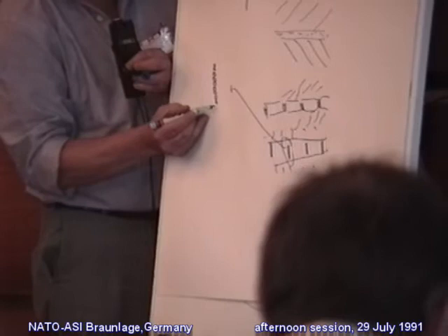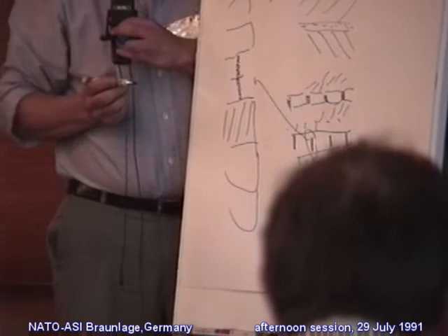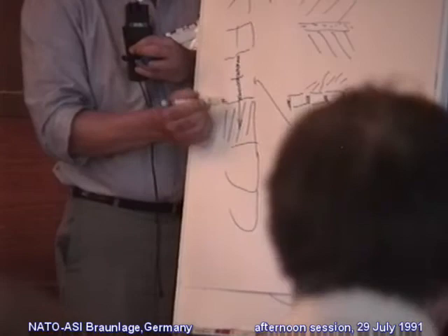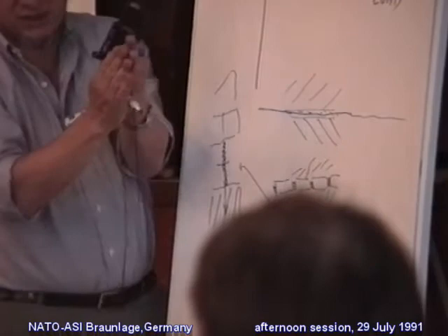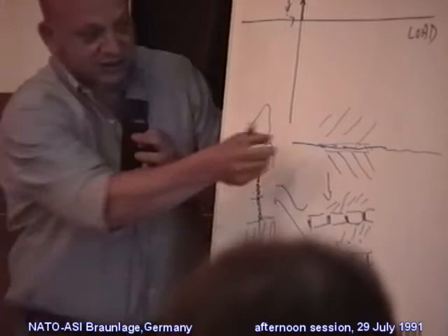And eventually I'll come to the point that I'll magnify this thing here, where I've got myself really a string of atoms, if you want, or maybe two of them here, but we won't quarrel about that. Here we have one surface, and here we have another, and this is the whole blocks of David Tabor. And eventually I'll snap something here, and this will not throw a big effect on this thing here. So, in other words, what you say, Jacob, is applicable if the separation will occur uniformly for the whole two things. What I'm saying is that it doesn't have to separate this way, and this will be a very adiabatic route for separating the two surfaces. It will avoid these catastrophic things and throwing the waves. So it may occur actually in real situations.